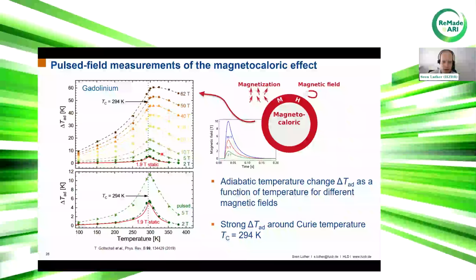Here I'm showing the adiabatic temperature change depending on the initial temperature, measured in different fields, from an applied field of 2 Tesla, 5 Tesla, up to 62 Tesla. As you can see here, the highest adiabatic temperature change is usually at the Curie temperature of 294 Kelvin for this gadolinium material. And as you can see, the magnetocaloric effect is also always a good tool to measure phase transitions in certain materials.